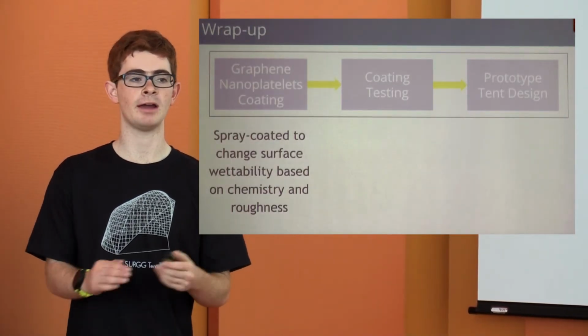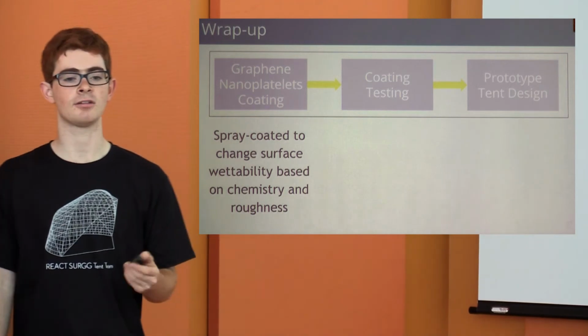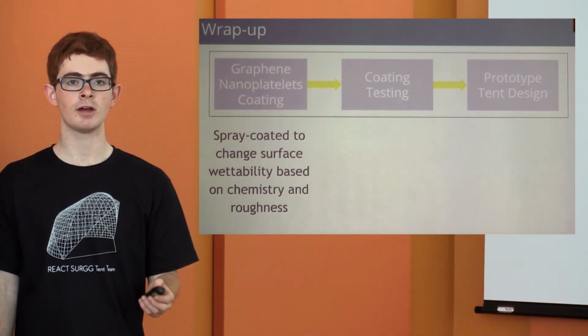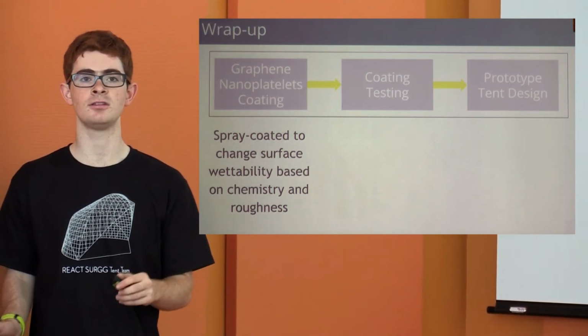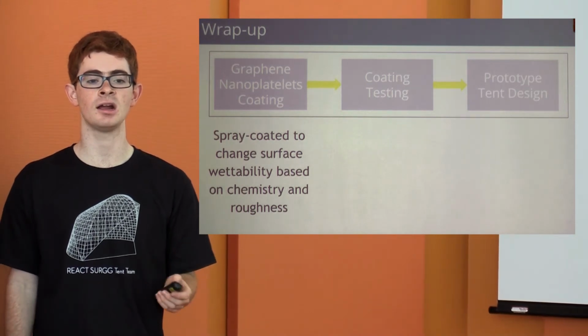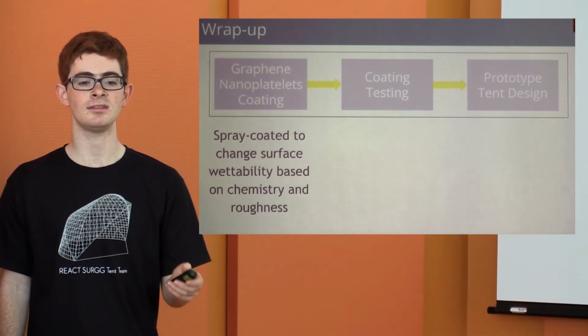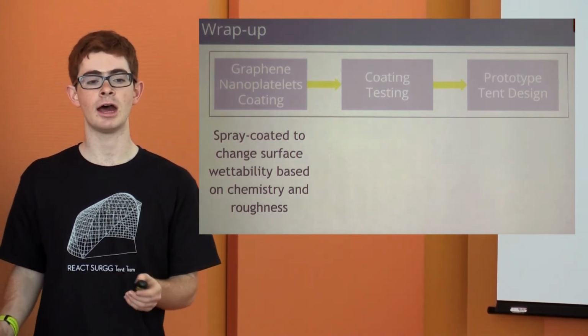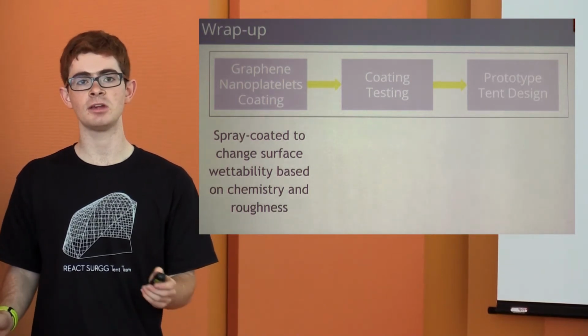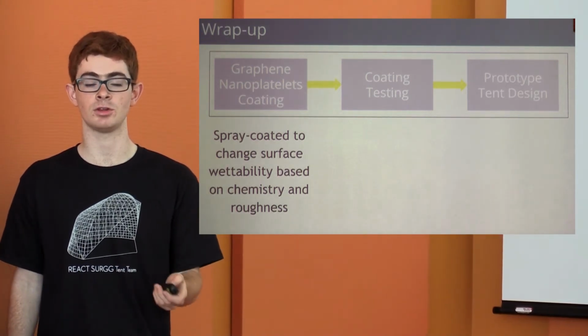And then to wrap up everything, we started by looking at graphene nanoplatelet coatings. Graphene nanoplatelets were spray coated to the surface of 110 denier PET (polyethylene terephthalate), and then we saw how the wettability changed based off both the chemistry and surface roughness.